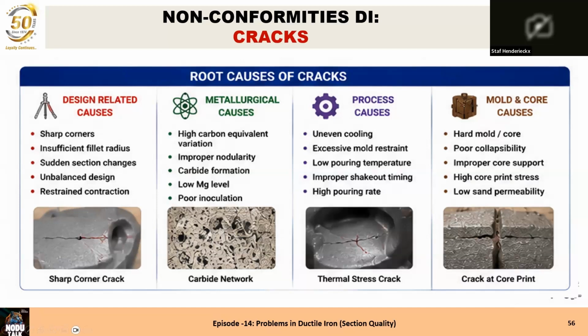Carbide formation can also act as a starting point. Low magnesium level, that means the same. If you have a low magnesium level, you have an improper nodularity. And poor inoculation, then when the nodule count is very low, the crack grows very quickly, because a crack grows from one nodule to the other. If there are only few nodules, the crack length will be immediately higher, and the higher the crack length, the quicker it goes further. Process causes: uneven cooling, of course.